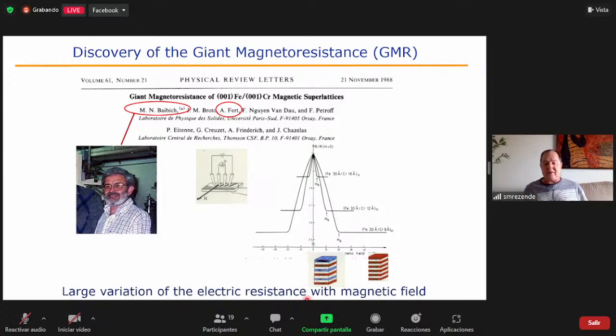They measured the resistance across the multi-layer that was made in such a way that neighboring magnetic layers have the magnetization in opposite direction, like this. This can be controlled by the thickness of the metallic interlayer. So what they did was to measure different multi-layers with different thickness of the chromium spacer. By applying an external magnetic field, the resistance changed, and the change was very large for a chromium interlayer with thickness 9 angstrom.